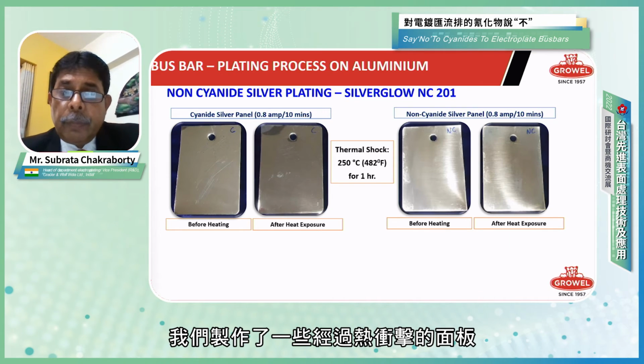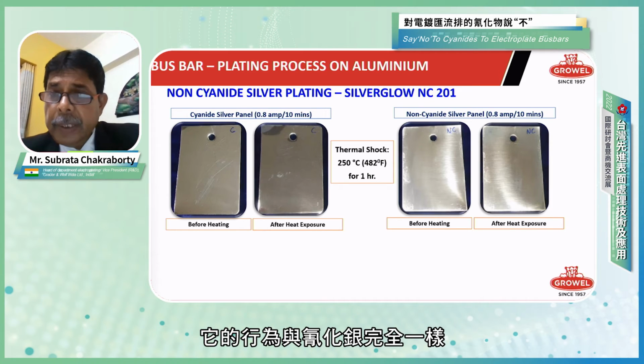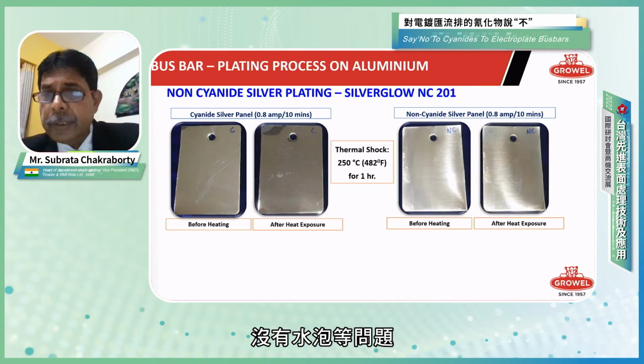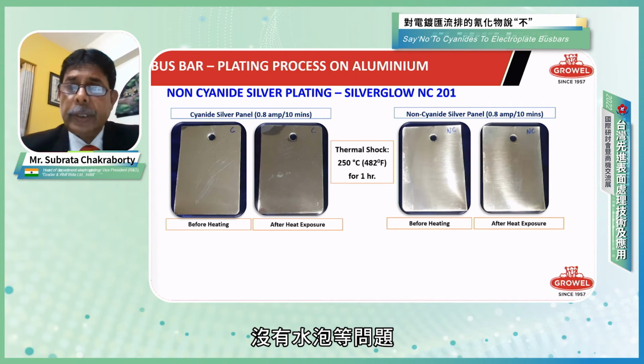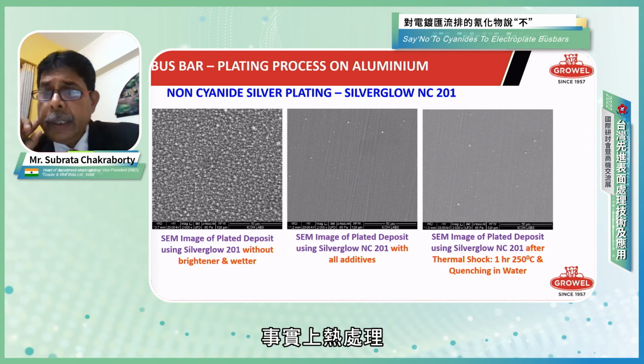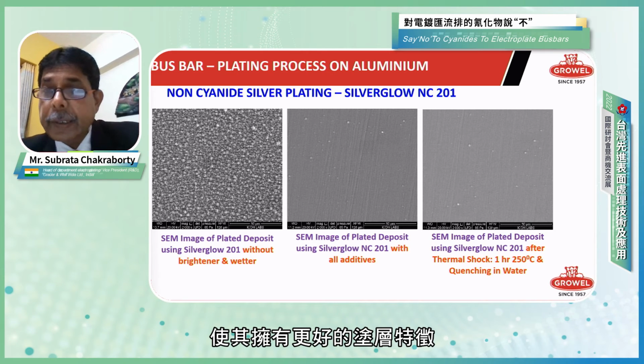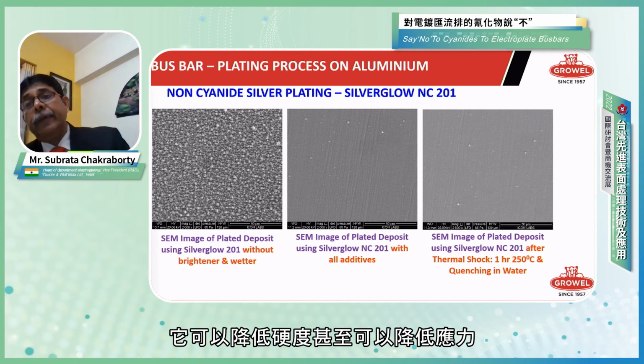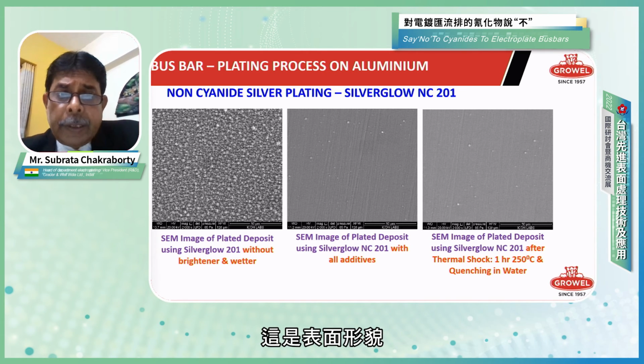Here we just made some panels with thermal shocking, and we see it behaves exactly like silver-based cyanide silver, so no problem of blisters and so on. In fact, heat treatment makes the coating characteristics better, as it can reduce the hardness and even reduce the stress. Well, this is the surface topography.